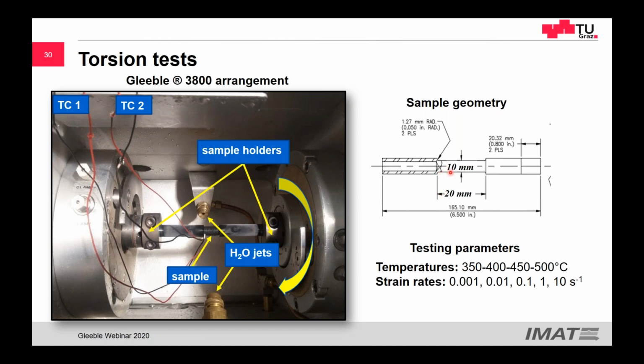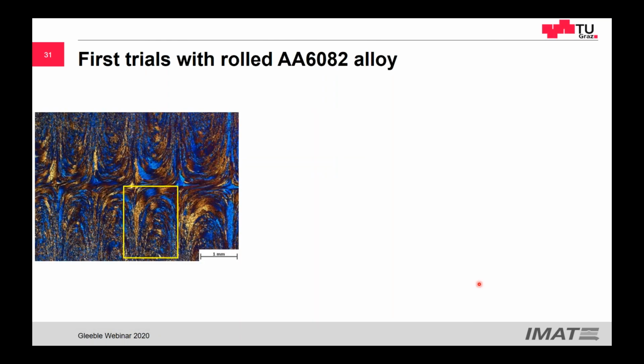So we may have in aluminium alloys only 5 degrees from the center to the border, which is, I think, very good. In other materials like steels and titanium alloys, we have a bit larger gradient of temperatures. So we did, as always, test a large amount of temperatures and strain rates. And we started with a hot rolled material with very large grains. And this is what we got.